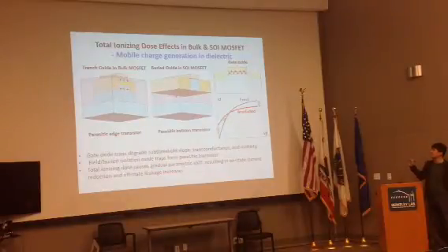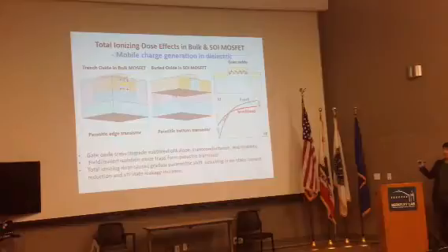So there's effectively another gate in between the gate region and the channel region. When defects or positive charges are trapped inside the gate dielectric, whose role is just blocking the channel and the gate while transferring the electric field from the gate to the channel, these positive charges or defects generated in the gate dielectric are very close to the main channel surface.